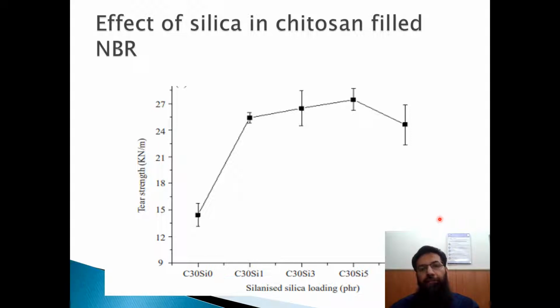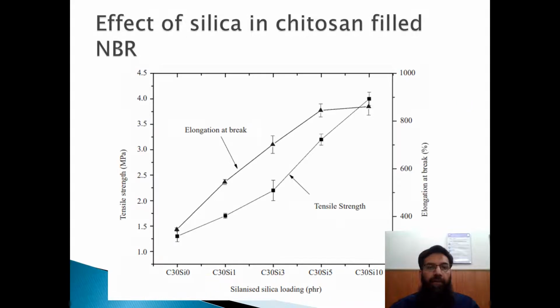So we can see that in the acrylonitrile butadiene rubber, where we have added the chitosan as our bio filler, if we add the silica, we can get the better properties as compared to only the chitosan, which is present at the loading of the 30 pHr. So similarly, the other properties, just like the tensile strength and the elongation at break, that also increases with the increase in the loading of the silica.